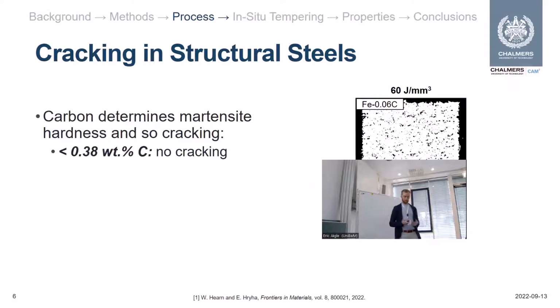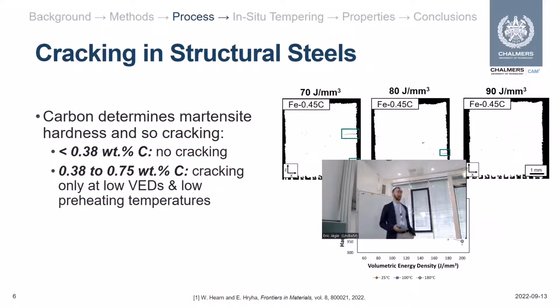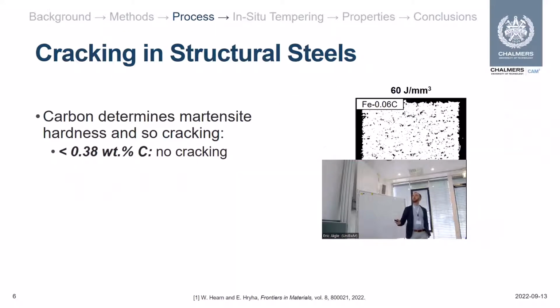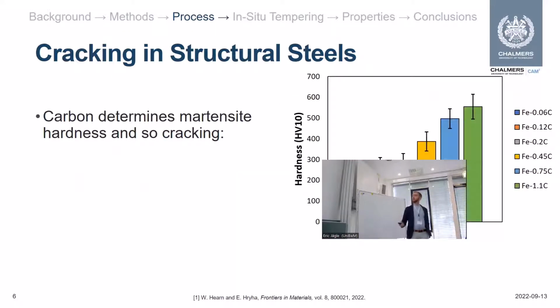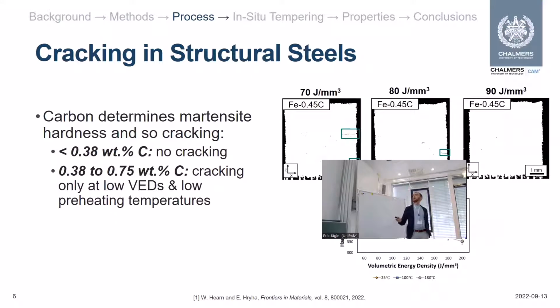When we start going a bit higher, about 0.38 to 0.75 weight percent, you see that cracking is happening in alloys, but only in ones produced at low volumetric energy density, as well as low preheating temperatures. And as we increase either of these factors, you see not only the size, but the number of the cracks generally diminish as you increase your VED. And eventually when you use a high enough parameter, the cracks go away.